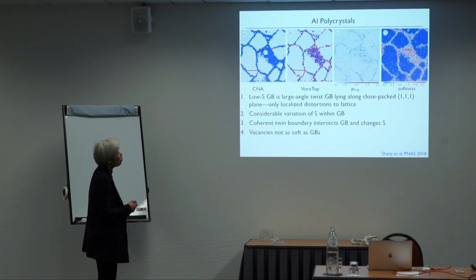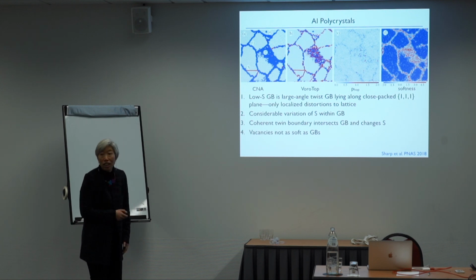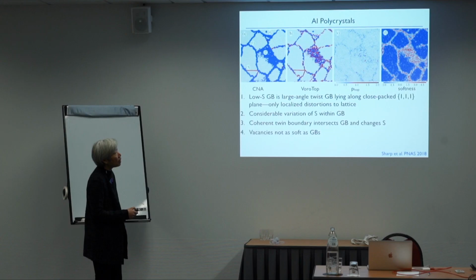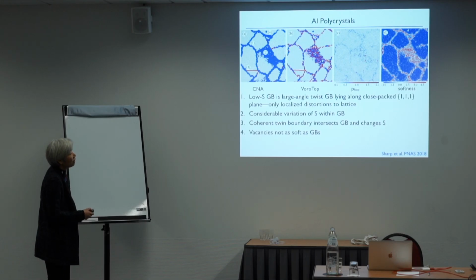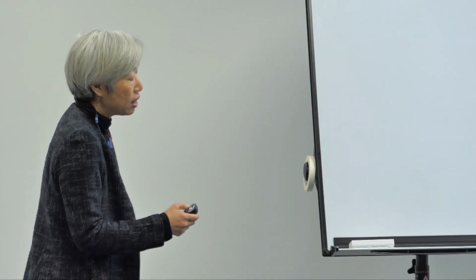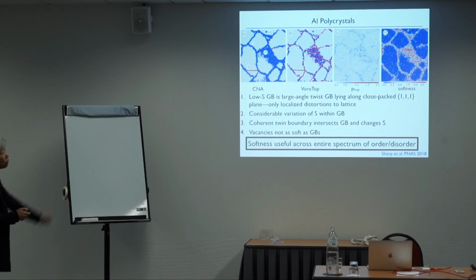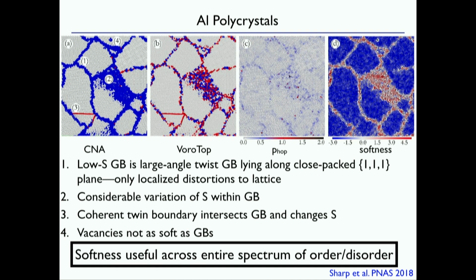And this is the standard measurement of crystalline order. This is softness. So you see softness is really low in the crystalline regions and it's higher in the grain boundaries, but it's not uniform. It's not like every particle in the grain boundary has the same softness. And there are cool things, certain things that are not crystalline, but they're not soft. There are various things you can say that are interesting for people who look at polycrystals and think about dislocations and grain boundaries. I'm not going to get into that, but let me look at this system. Oh, what this says is that since we can pick out the grain boundaries, we find that the soft particles are in grain boundaries, and that certain vacancies that we know are not important from polycrystals are not soft.